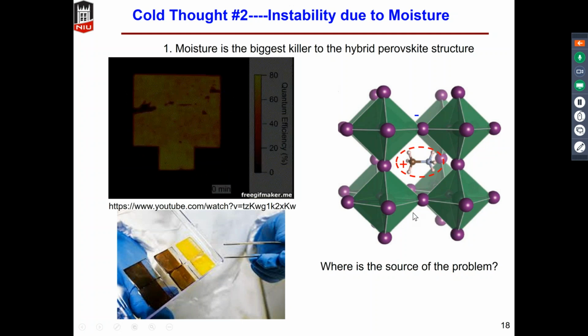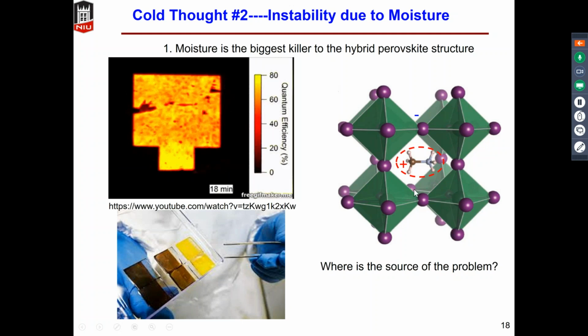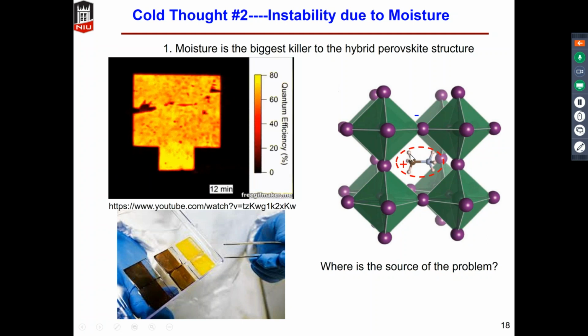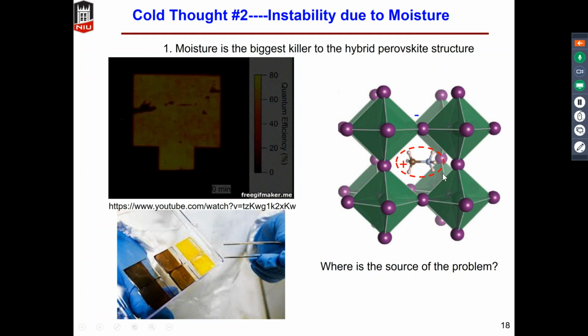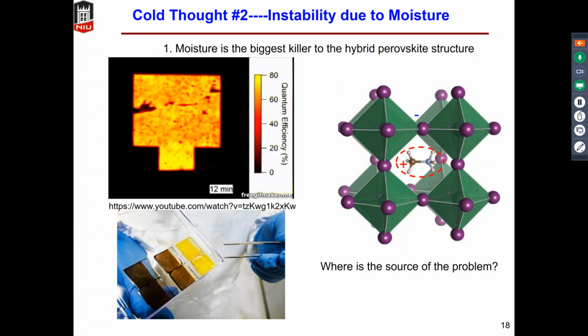And the reason behind this degradation process is the methyl ammonium, which is highly water soluble. So the water can easily hydrolyze it because it carries a net positive charge. When the positive methyl ammonium is washed out by water, then the remaining negatively charged inorganic framework collapses. So this is the general reason why this material is so vulnerable to water.